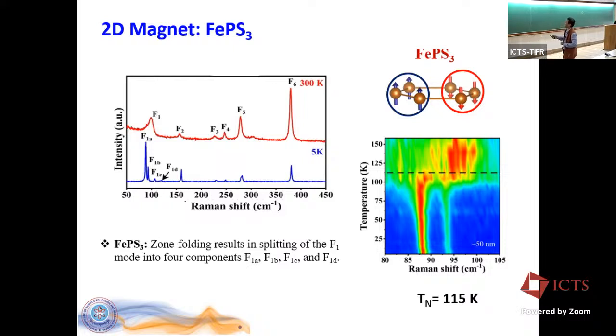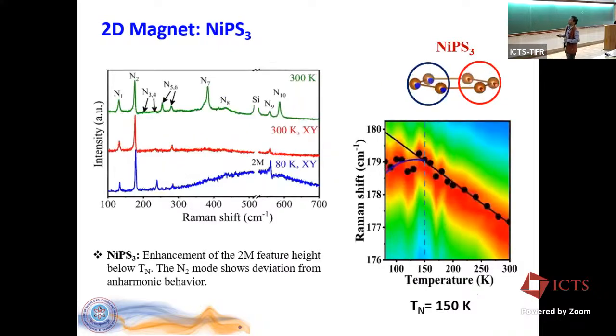And here is the color map to tell you the temperature at which this transition happens. So this is the paramagnetic phase, and this is the antiferromagnetic phase, where you see this broad feature. Basically, there are these multiple peaks. So we're just plotting these 2 here, just to ensure that we see clearly. All right. Then NiPS3. So NiPS3 has 2 very clear signatures of the antiferromagnetic ordering.